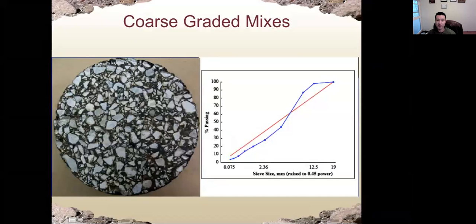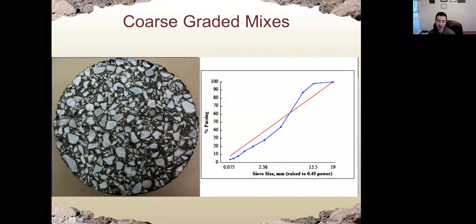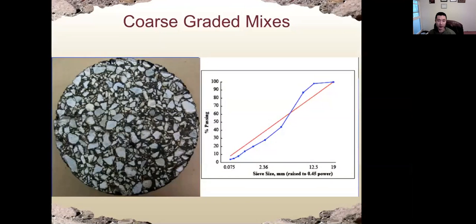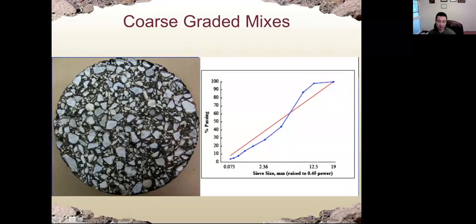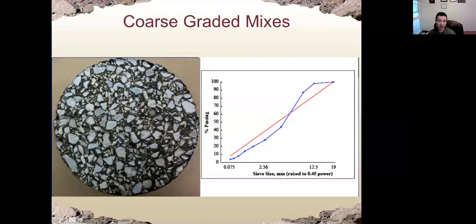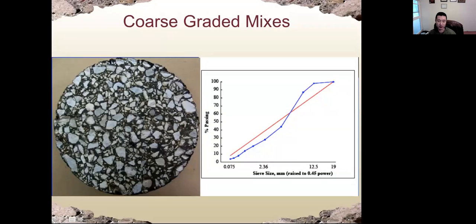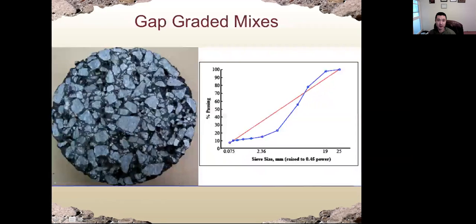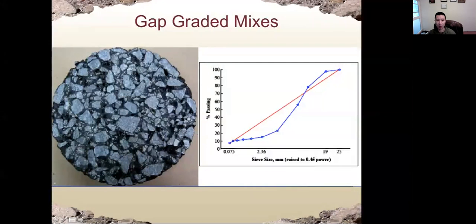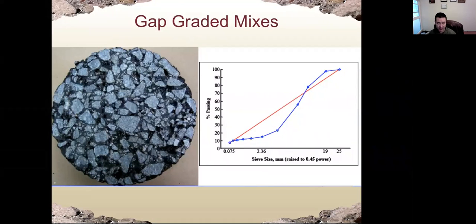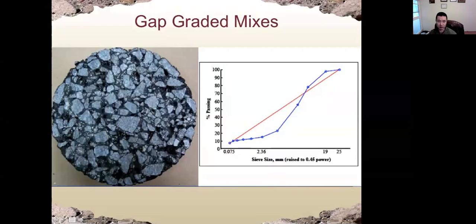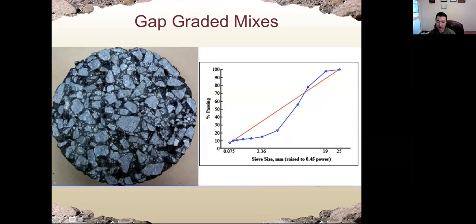The next one is called coarse graded mixes. It also belongs to the well-graded category, the second category. In this gradation, both coarse aggregate and fine aggregate will work together. They will take the load together. For coarse aggregate, because we have a higher percentage of coarse, we have some particle-to-particle interaction, contact between coarse aggregate. And this one, we can see, obviously we have much more percentage of coarse aggregate, and we call that gap graded mixes. So for gap graded mixes, the coarse aggregate is in control. They take the majority of the load transferring. So we have a lot of particle-to-particle contact between coarse aggregate.